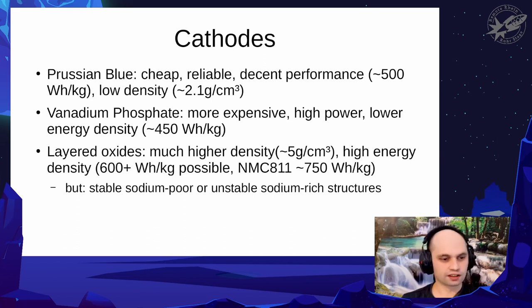There's a second material that is very popular. It's vanadium phosphate. It's great for very high power applications. You can charge and discharge at 10C or 20C thousands of times with that material, but it has a much lower energy density, or somewhat lower energy density, especially at high power, it's much lower. But it works. It has been developed by Tiamat in France, and actually it's originally from lithium that has been adapted to sodium.